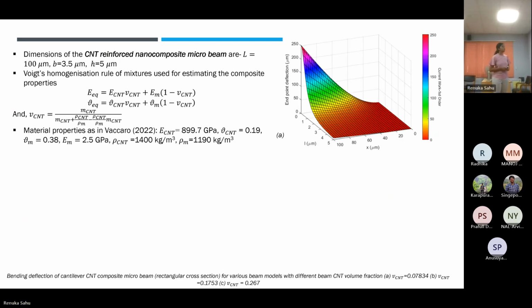Here we get these bending deflections, using the first order results. We can see the variation with respect to the material length scale parameter L, starting from 0, where we have the maximum endpoint deflection representing the classical case, moving to 5, which is the same value as the thickness of the beam. You can see how the endpoint deflection varies for different beam coordinates and different material length scale parameters.